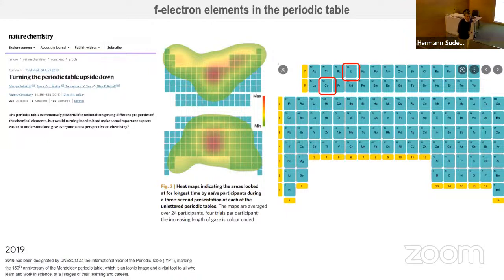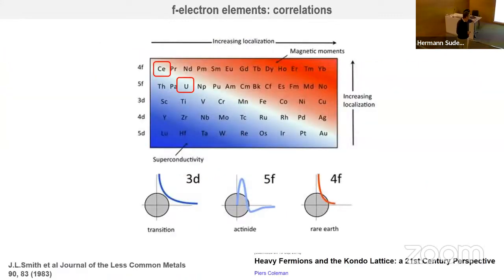So this small exercise just tells you that it's interesting to take a look at this part of the periodic table. And the two elements which I would like to focus on are these two here, uranium and cerium. And why these two elements? We can see this if we take a look a little bit more at the physics. These are the wave functions, how localized they are. The transition metals are more or less spread. 5f electrons are a little bit more spread. And in the case of 4f, they are pretty much localized. Now, when you increase the nuclear charge, you shrink this, and it happens that the f electrons become localized, and therefore you get magnetism.